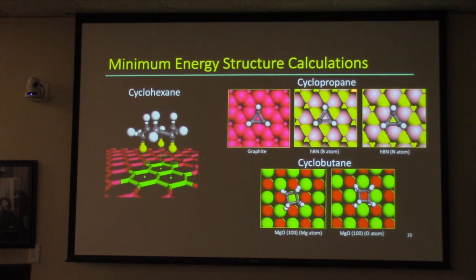And so here, for example, cyclopropane, which we just studied, you can see that it really likes to sit on graphene and boron nitride. And it can either choose to sit, in this case, a top boron or a top nitrogen. And those simulations really show that. You can notice that cyclobutane likes to find regions where it fits in the crack. I should tell you, this is the only one that's not distorted. All of the other ones are slightly distorted, so they're not perfect squares or cubes, etc.